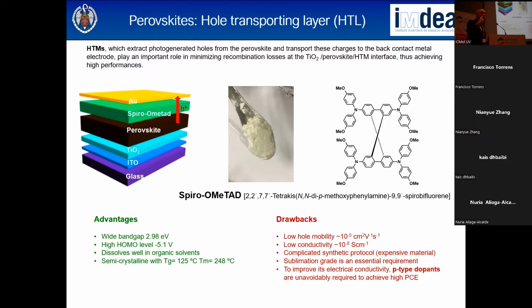If you go to Merck, it was around 500 euros per gram. Now, there are other companies where you can get it for around 350 euros per gram. But in addition, you have to use it in sublimation grade. So you have to sublime it and you lose material. So it's really very expensive, and therefore it's difficult to apply for device fabrication.